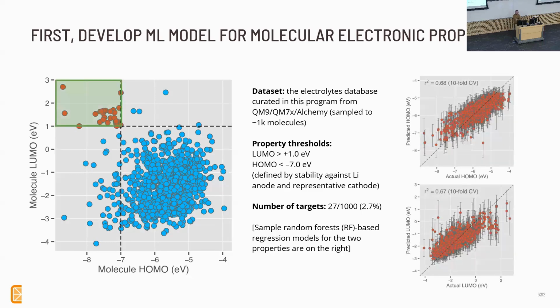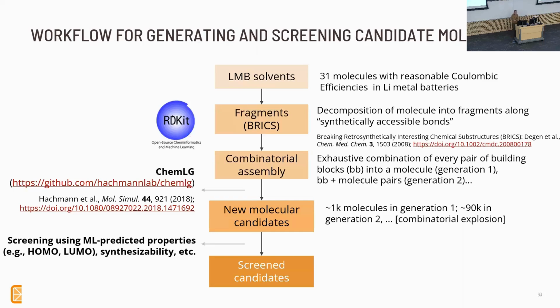There you go. And we were able to make some models for the good HOMO LUMO, basically. And this is against the entire data set. And you can see that we do a pretty good job of predicting within the range that we care about here pretty nicely. But that's the first step.